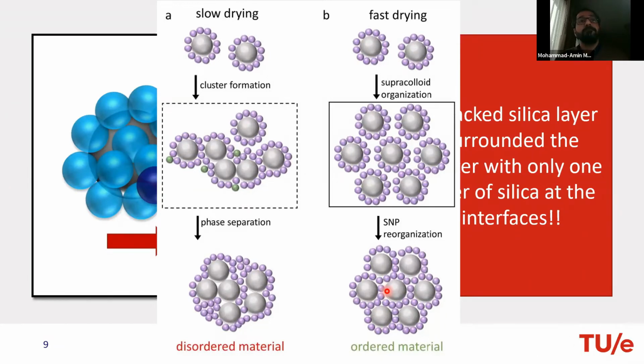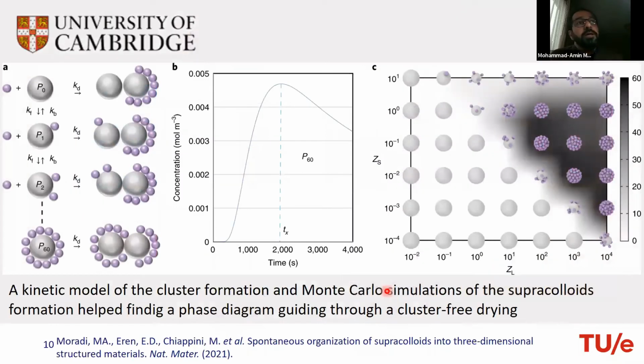So we also asked for some help from collaborators, Professor Alex Routh of Cambridge. He wrote a kinetic model for the assembly, telling us how we should approach this assembly and when this clustering happens in our systems. According to his calculations, the maximum of the fully covered particles without the clustering in the system would happen at 1800 seconds since the mixing happens.